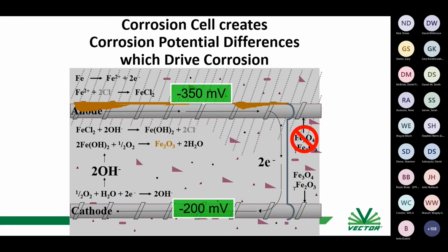So it's hard to generalize, but it could be, for example, a situation where you have a crack in your deck and you've got chloride contaminated water seeping through that crack, and both the top mat and the bottom mat of steel get contaminated with chlorides at that crack location. Or it could be a construction joint or something similar. And at that point, those are both going to be acting as anodes.